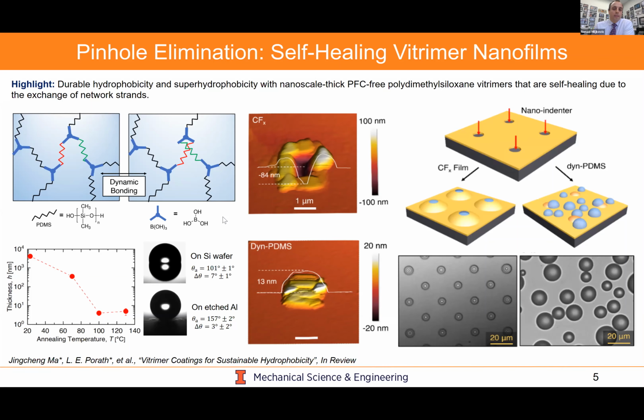We then take these and study them using atomic force microscopy, and we could indeed show that pinhole density can be drastically reduced. And even if we induce pinholes via nano indentation, they could be removed. And then finally, by inducing pinholes with nano indentation, these rectangular arrays, we could compare our Dyn PDMS films with CFX fluoropolymers, which are just your standard state-of-the-art film. And indeed, you see that for the CFX film, you form blisters, whereas our films will self-heal and droplets will form on top.